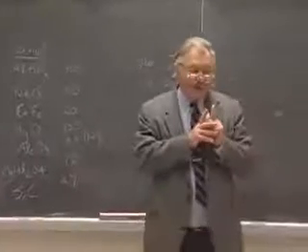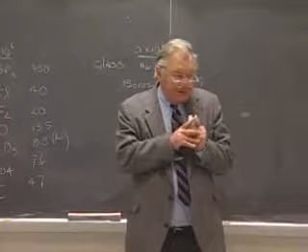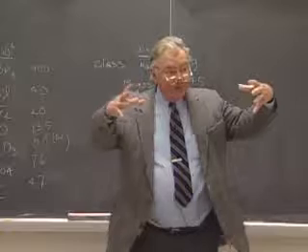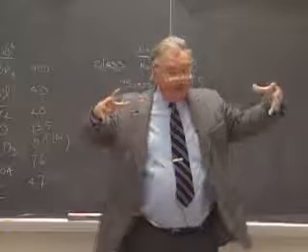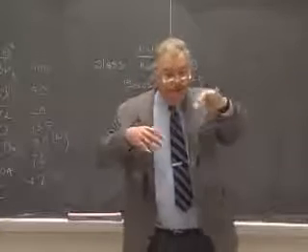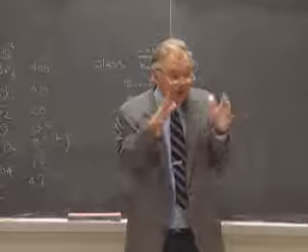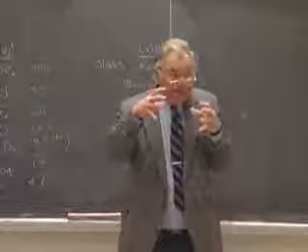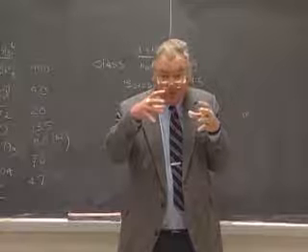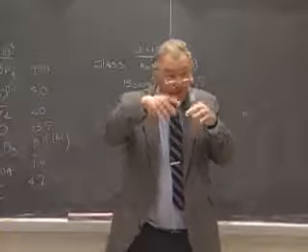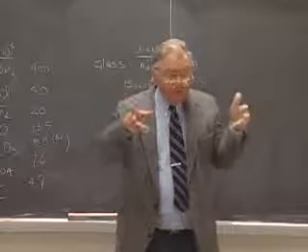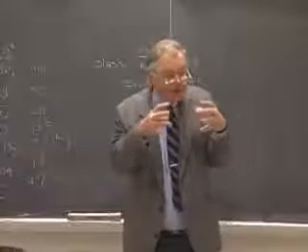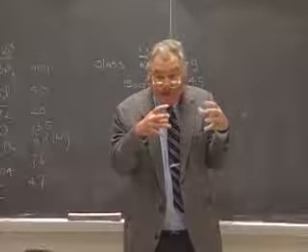And the reason lies in the nature of the structure. Something like MgO has ordered ions, and when you heat it up, it expands isotropically. A glass is this random network of corner-shared polyhedra. So when you heat it up, yes, the dimensions of the polyhedra increase in proportion to the change of temperature, but the framework, because it's so meandering and open, can buckle to accommodate the increased size of the tetrahedra that are in the linkage.